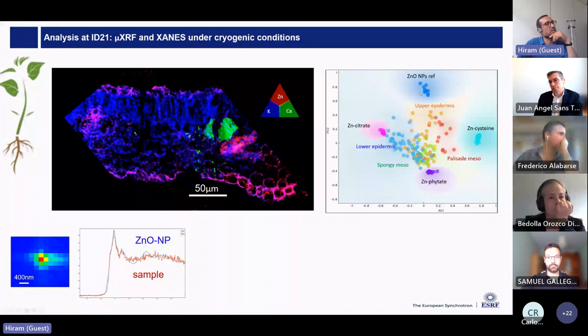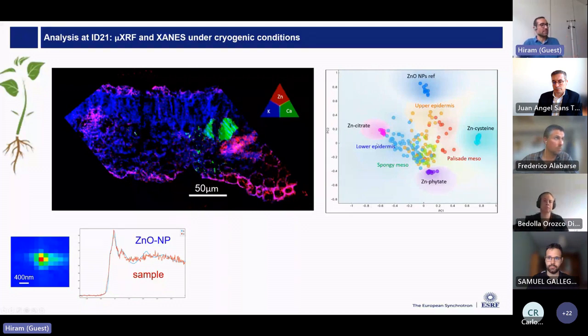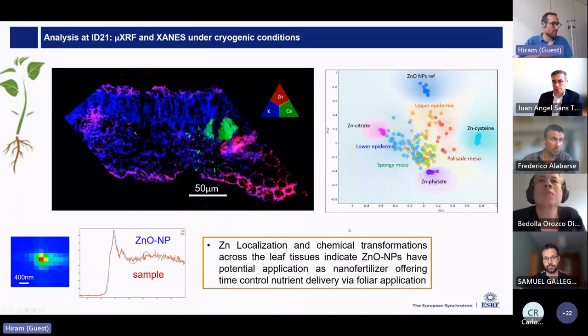So for example, this is the initial condition, like the zinc oxide nanoparticle. When you are in the upper epidermis, so in the top part, you have much more of it, which is still zinc oxide. And as you move through the layers, first you go to a speciation which resembles the cysteine. So SH group sulfur is playing a role in the palisade zone. But as you go to the lower layers, then you have mainly carboxylates like phytate and citrate. And being able to do this identification of the chemical transformation across the different tissues allows us to see that the zinc is released from the particles, and it's actually a source of zinc for the plants. So it has potential applications as nanofertilizer.